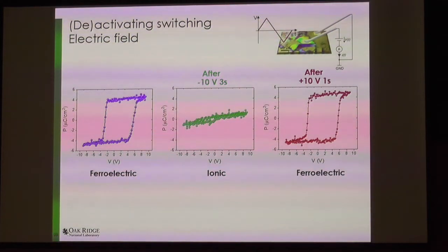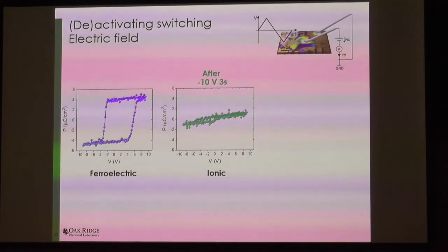Hi, I think it's a very interesting system. I'd like to offer a different possible interpretation. Rather than saying that the polarization switches backwards, I wonder if this is a case where it really switches forward onto the next value of the polarization lattice. In other words, it looks to me like this may be a case of what's called quantum adiabatic charge transport. When you go around the cycle, you've really actually moved a copper 2+ ion up one layer, and it's carried charge with it, and it's basically carried you from one value of the polarization lattice to the next at the end of the day.